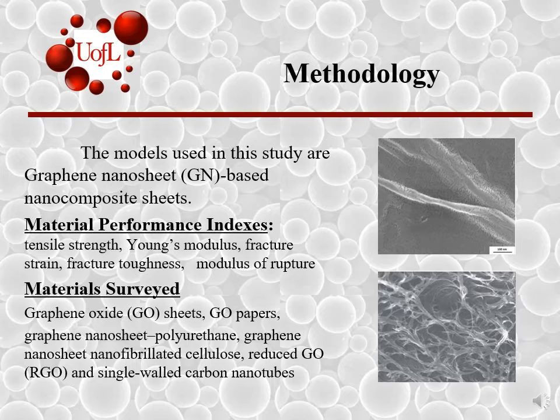This review paper used multiple different models because of the multiple studies, but all models used were some form of graphene nanosheet-based nanocomposite sheets. Material performance indexes used were tensile strength, Young's modulus, fracture strain, fracture toughness, and modulus of rupture. And the materials surveyed were graphene oxide sheets, graphene oxide papers, graphene nanosheet polyurethane, graphene nanosheet nanofibrillated cellulose, and reduced graphene oxide and single-walled carbon nanotubes.